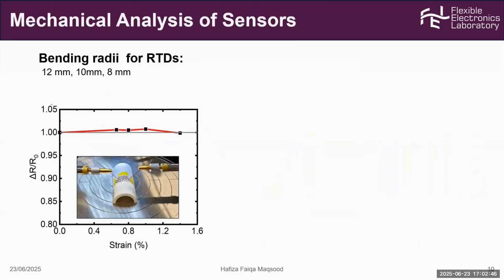In order to study the mechanical properties, we also performed the bending test at different bending radii with a minimum radius of 8 mm. The strain was calculated at each bending radius, and as you can see in the plot, there is a slight increase in the resistance during bending of the RTDs, which is likely due to strain-induced deformation causing the copper to become more resistive while bending.